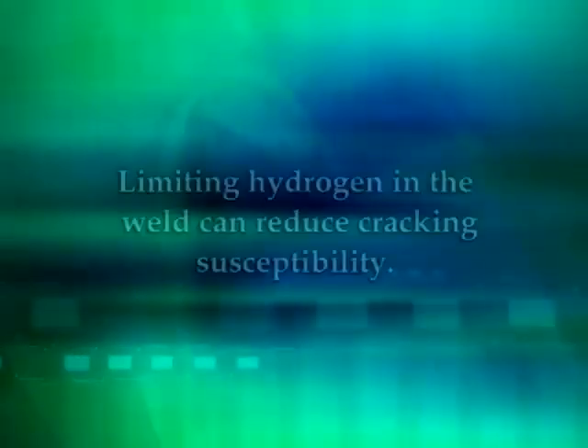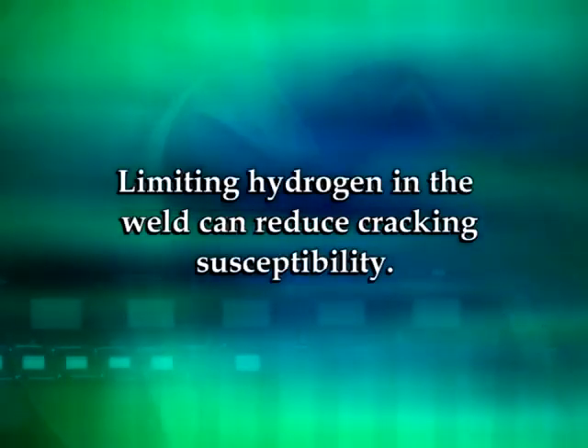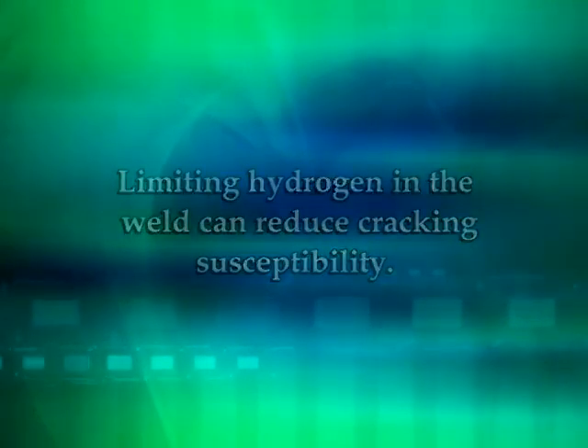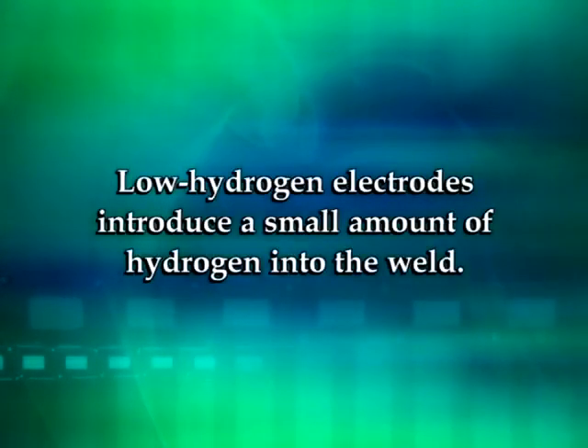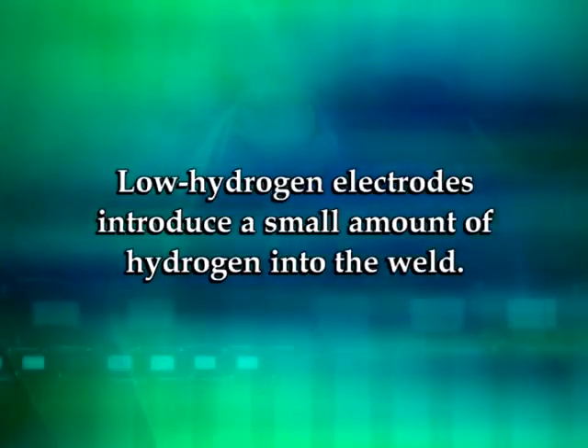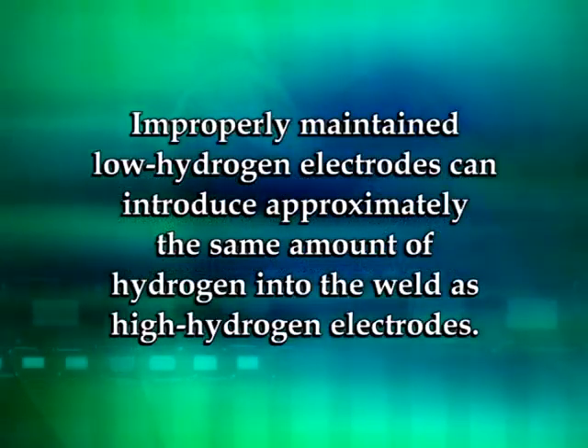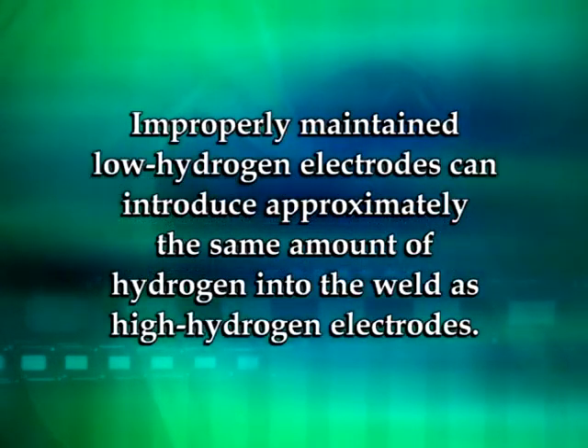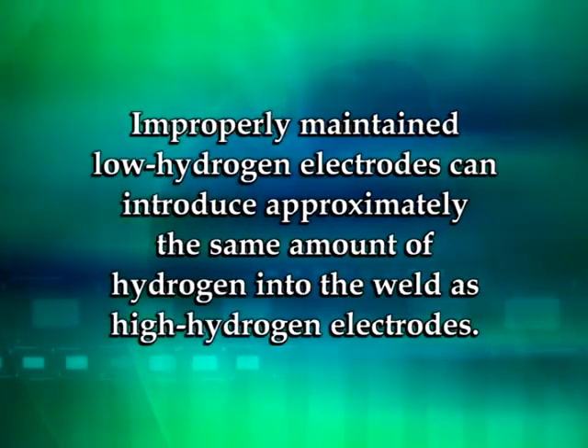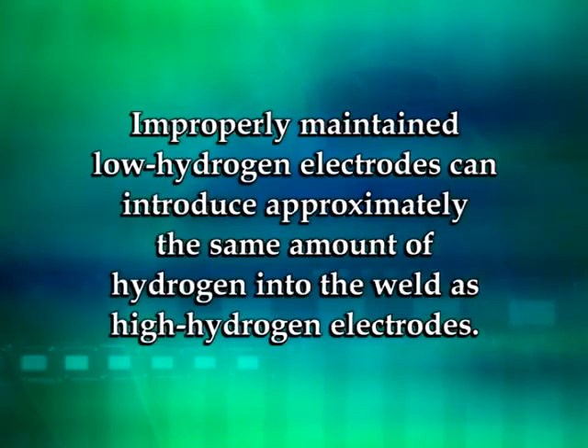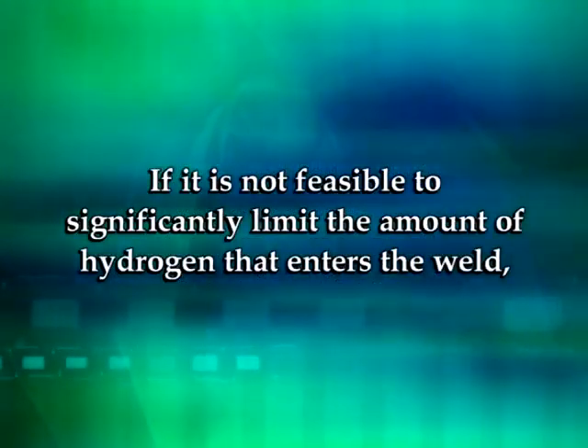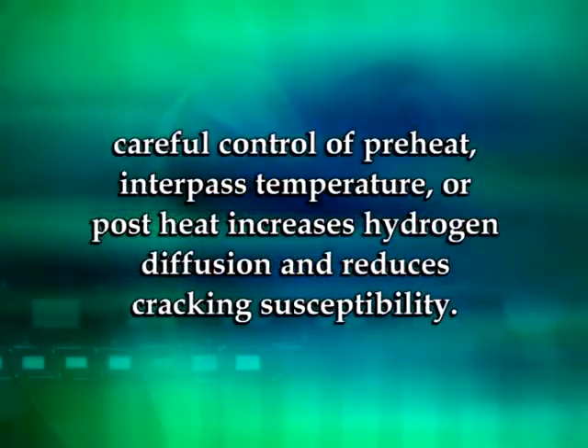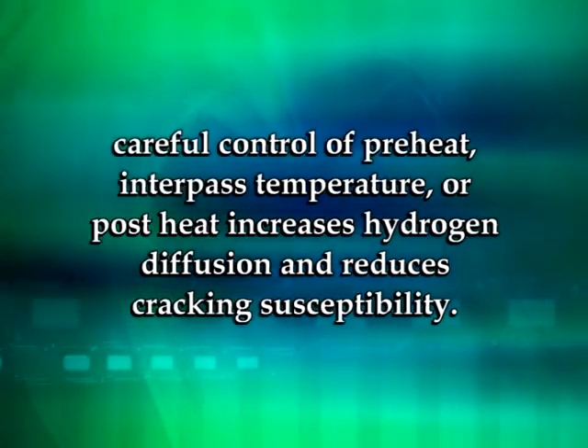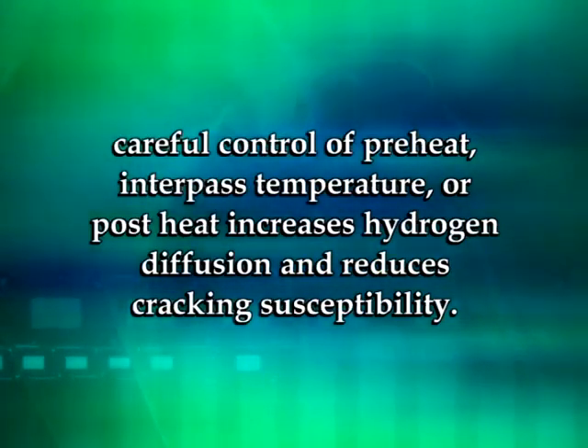So remember, limiting hydrogen in the weld can reduce the hydrogen cracking susceptibility. We've demonstrated low hydrogen electrodes introduce a small amount of hydrogen into the weld. However, improperly maintained low hydrogen electrodes can introduce approximately the same amount of hydrogen into the weld as high hydrogen electrodes. Finally, if it is not feasible to significantly limit the amount of hydrogen that enters the weld, careful control of preheat, interpass temperature, or post-heat increases hydrogen diffusion and reduces cracking susceptibility.